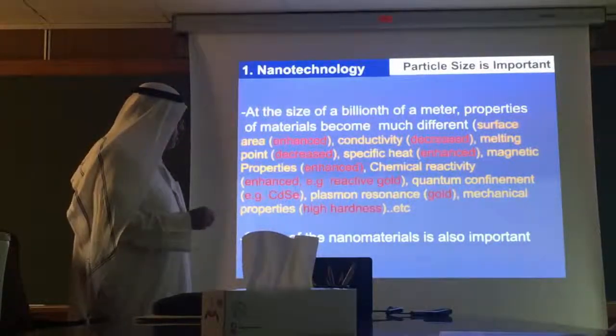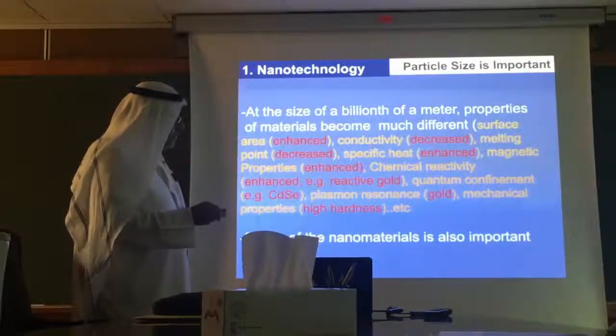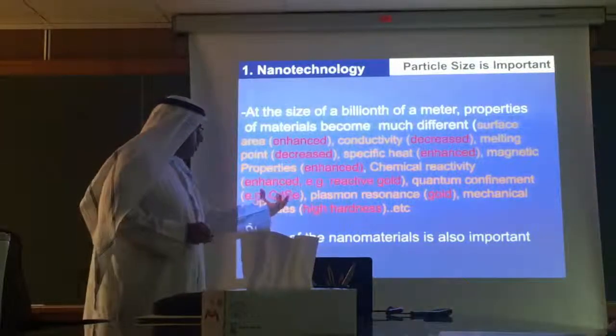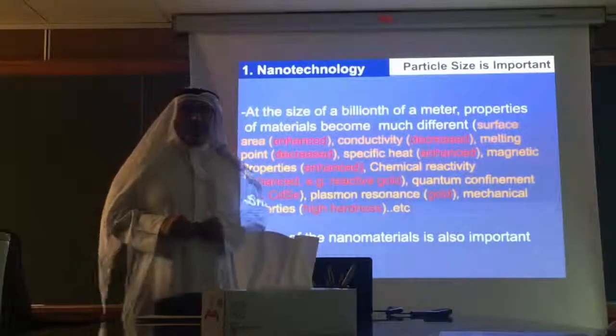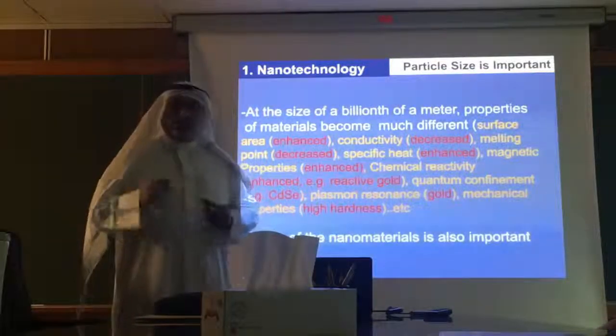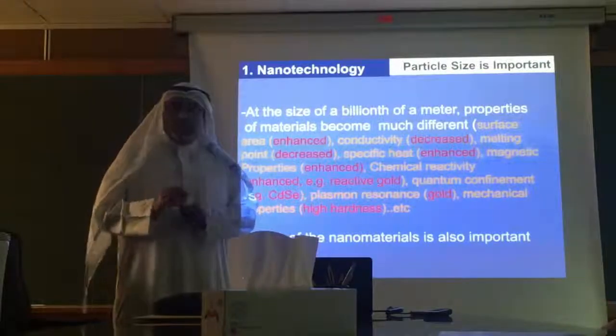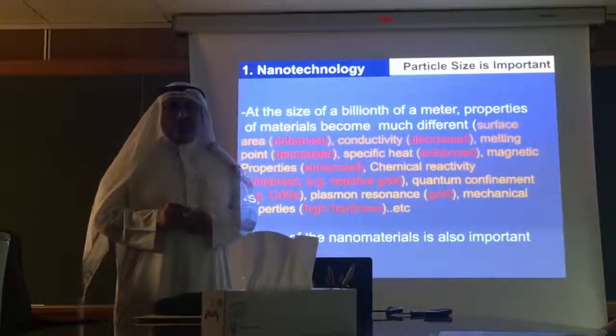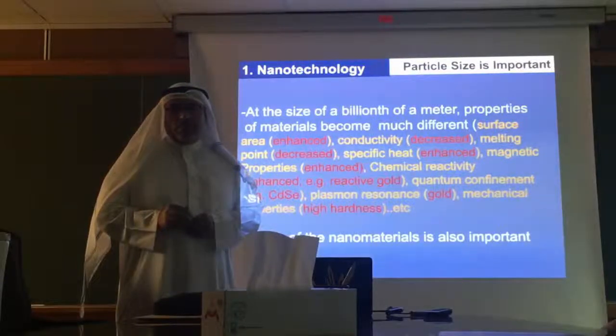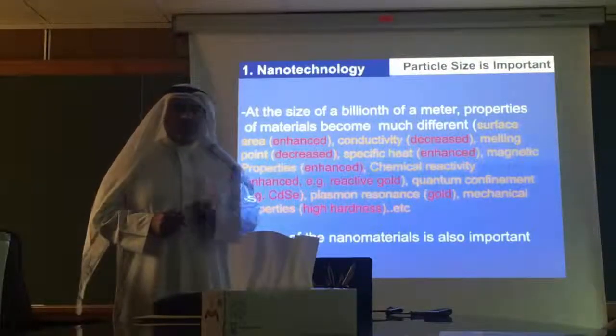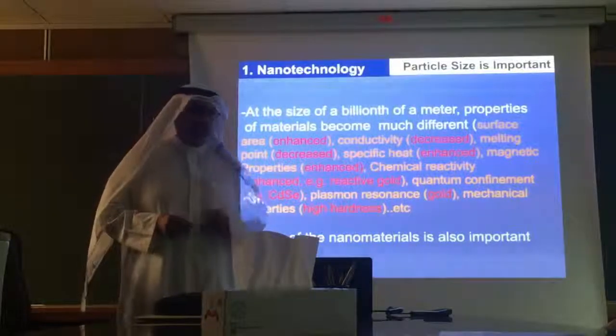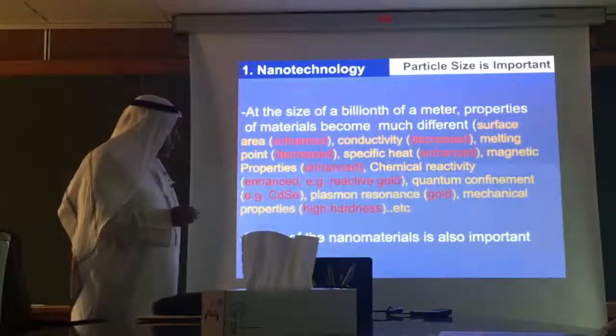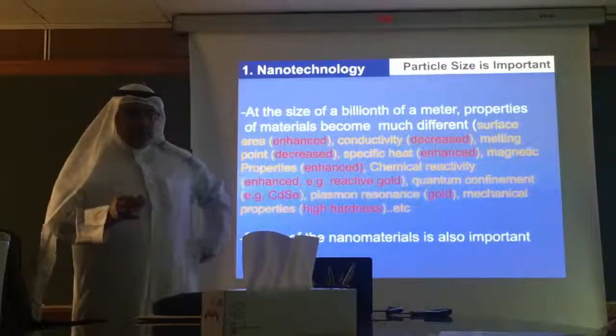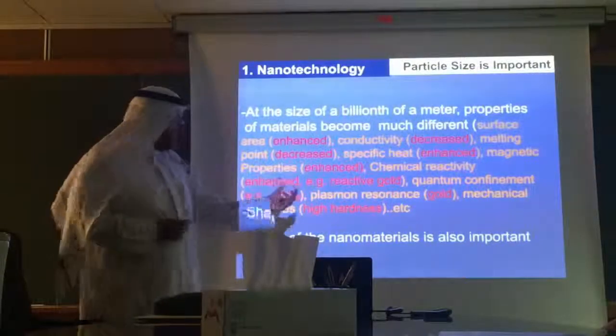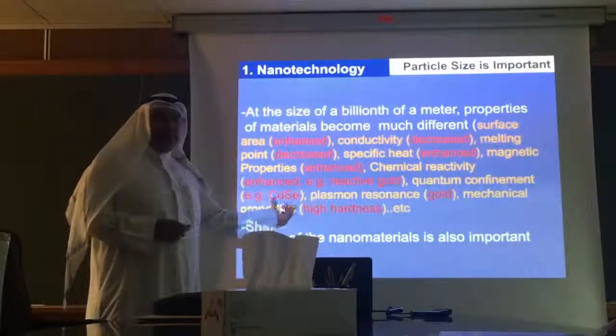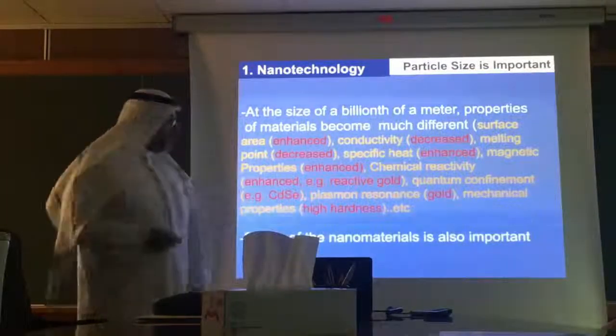The quantum confinement, this is very much related to physics. I didn't do a lot in this field, but I'm sure you know cadmium selenide and cadmium sulfide. When you make it into very small particles, you confine the electron to a space, and this will give excellent properties to the physical properties, and this is called quantum confinement, or they call it quantum dot, which has many interesting applications. The colors, for example, change by changing even 1 nanometer in size. If you prepare 6 nanometer, it will give you orange, for example. If you make it 5, it will convert to become purple.